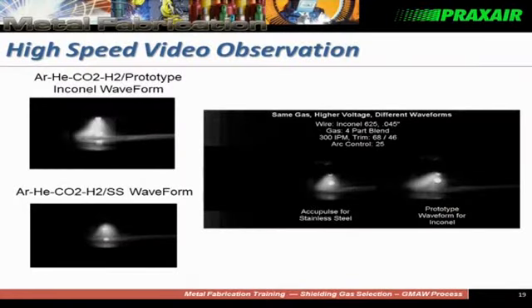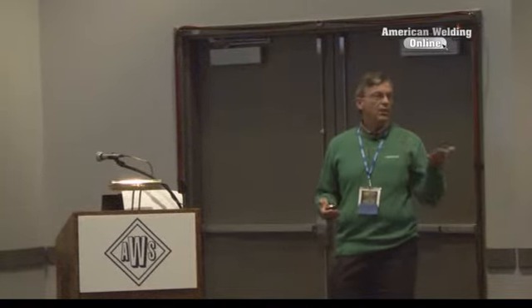This is just to give you a little bit of a visual picture. Again, here's the prototype waveform. What you can't tell here is that the bead shape is not too bad, but the surface is a lot rougher than this particular one here. So particularly with these high alloy specialty materials, bead shape and surface condition are very important. And if they're not flat, if they're fairly rough, they require post-weld grinding and other processing.